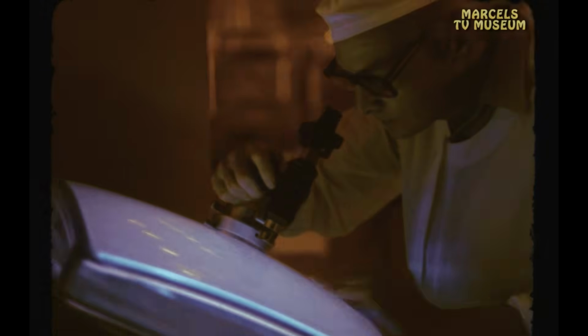Exposure to the ultraviolet light source hardens the fluorescent material. The unexposed material remains soluble and is washed away with deionized water. This leaves us with a regular pattern of about 650 stripes of fluorescent material for green. 2 more suspensions are applied in turn. For each exposure, the light source is accurately located in the position of the appropriate gun.